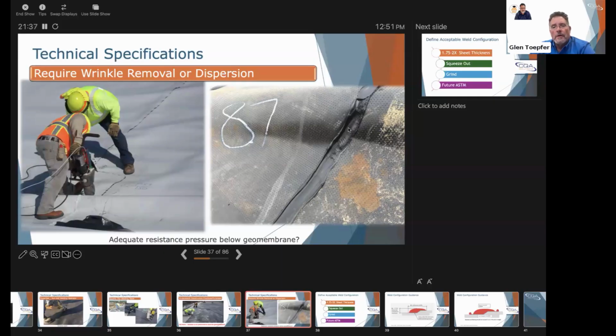Same here on the right. You can see the weld's starting to sink in there. They don't have the pressure. Maybe they lost their overlap there. It's hard to tell. It looks like there's separation, but you don't have that pressure, and that really should be required. A lot of times these wrinkles can be walked out. If they can't be walked out, then they should be cut out and repaired.